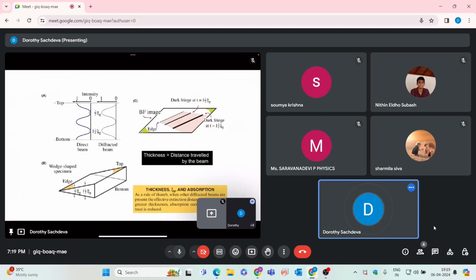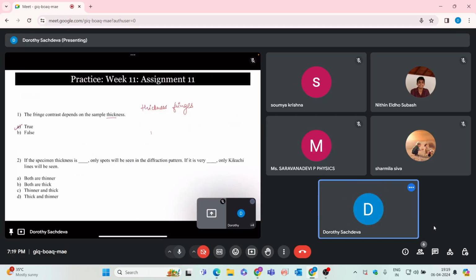The next statement, question number two, says: if the specimen thickness is dash, only spots will be seen in the diffraction pattern. If it is very dash, only Kikuchi lines will be seen. So we already discussed that for the Kikuchi lines, your sample should be thick enough, and your diffraction spots will be seen in a thin specimen itself.